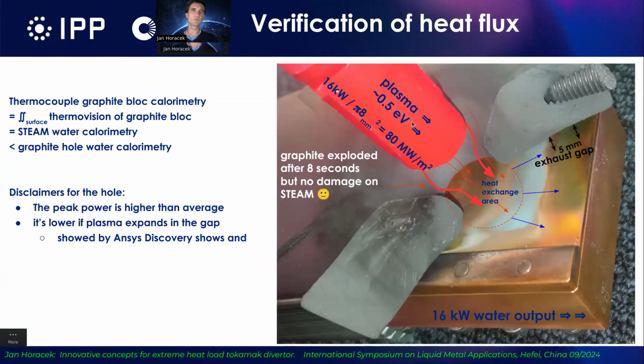We didn't believe it, so we tried to verify the heat flux using a different technique. So in front of the target, we put a piece of graphite with a hole in it, and then the plasma just flows through it and concentrates inside this hole. And then we said, okay, all the plasma exchanges its energy at this circle below the hole. So if you divide just the power which is absorbed into water by the area, you get 80 megawatt per square meter, which would be quite fantastic. And it survived for 8 seconds until the graphite exploded by thermal expansion.